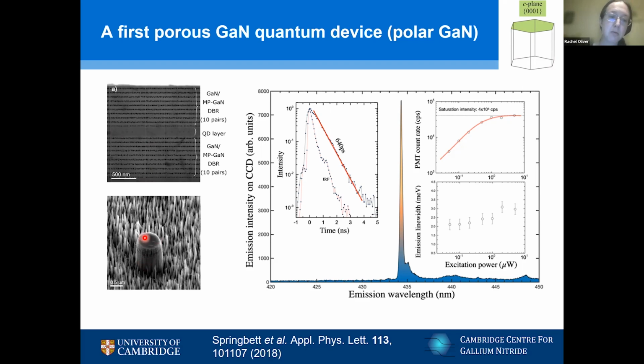So we've done our sphere lithography, but the porous GaN has really disrupted the dry etch used to form the micropillar and left us with these gallium nitride nanograss all around. Nonetheless, with the two DBRs in place and the pillar structure, we get very nice bright emission from these devices. We get a lot of counts per second. So we can see here's our nice bright dot. The design wavelength for the DBR was 435 nanometers, so we're quite close to that where we're seeing our brightest emission.